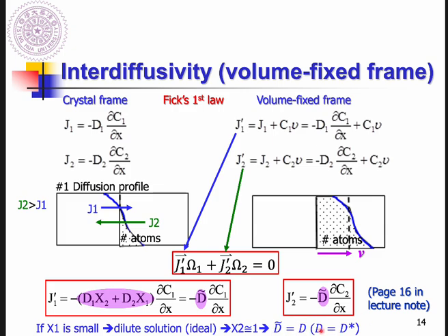In the previous slide, we also demonstrated that under the same conditions, intrinsic diffusivity equals self-diffusivity. So under an ideal or dilute solution, self-diffusivity equals intrinsic diffusivity equals interdiffusivity.